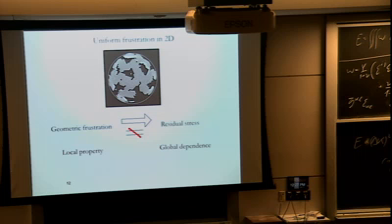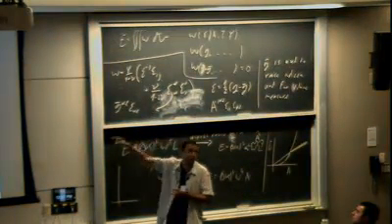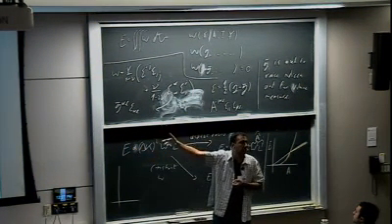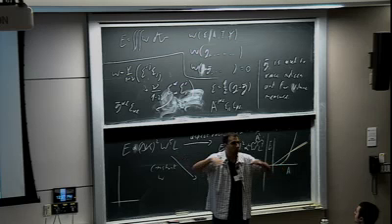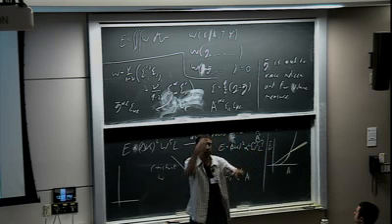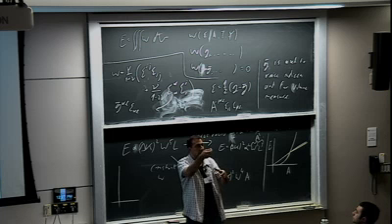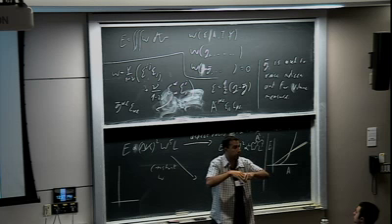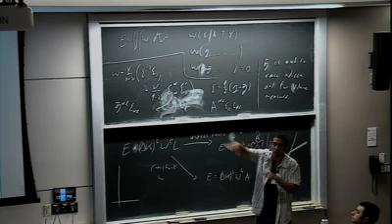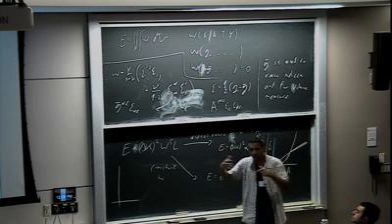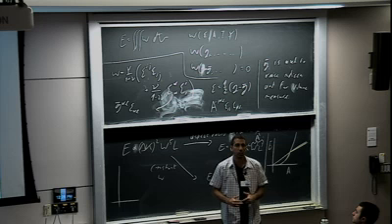What happens is that what I told you now is a way of resolving the frustration which was very smart. You were as close as possible to the reference metric. But imagine if I was just dropping these things onto the surface of the sphere and I was allowing defects. At a certain stage in time, you would acquire a sufficient amount of curvature to make a 5-fold defect. And once you make that, that accumulates a lot of curvature. And in addition, with all the rest of the guys around it, it approximates your surface. So that would be a very, very expensive but local resolution of frustration.